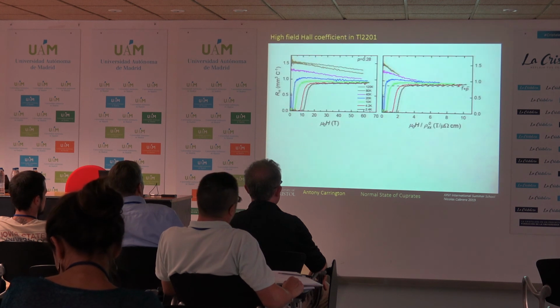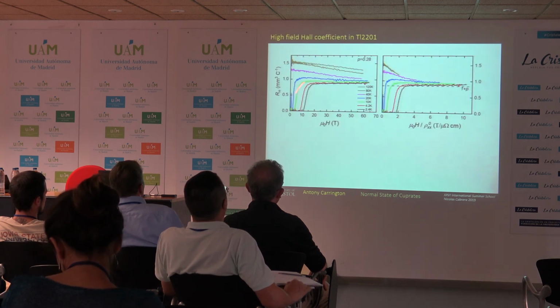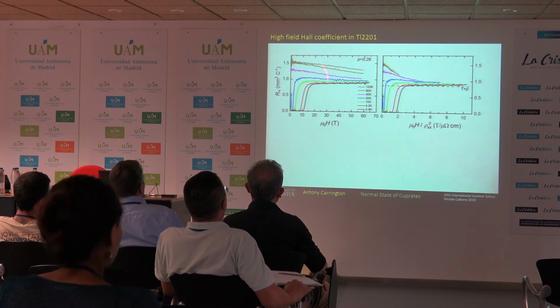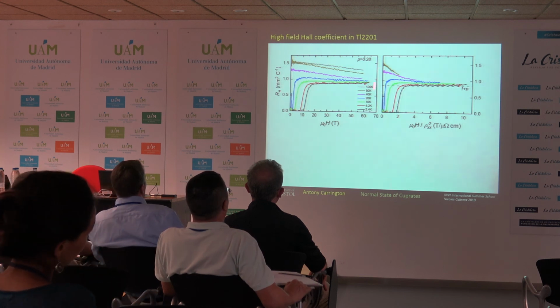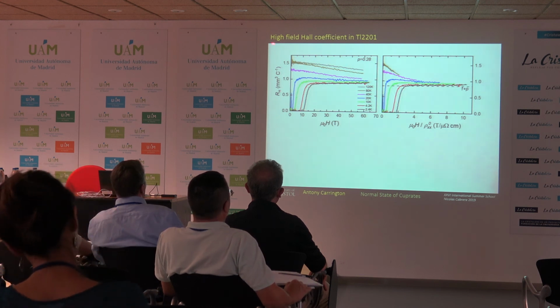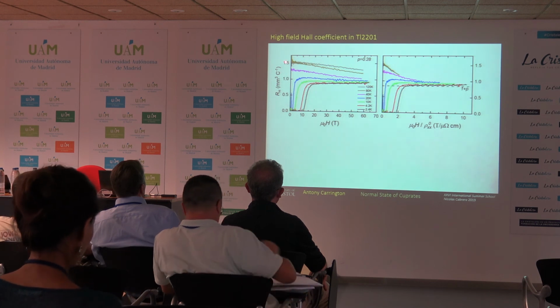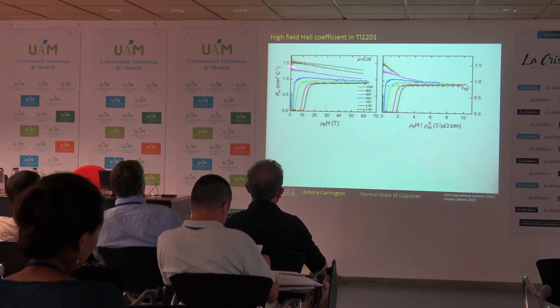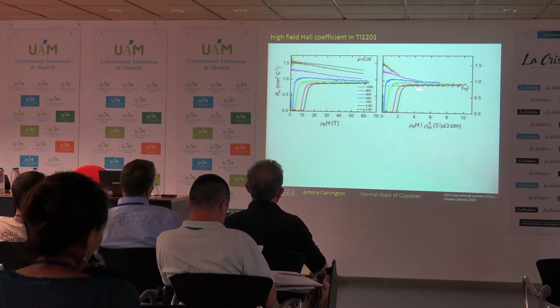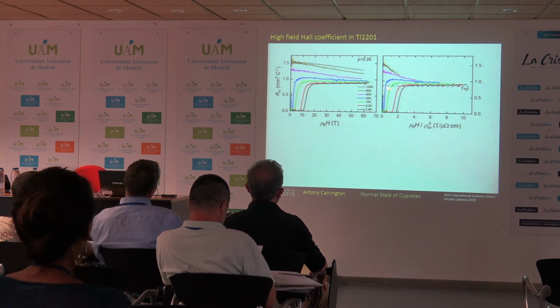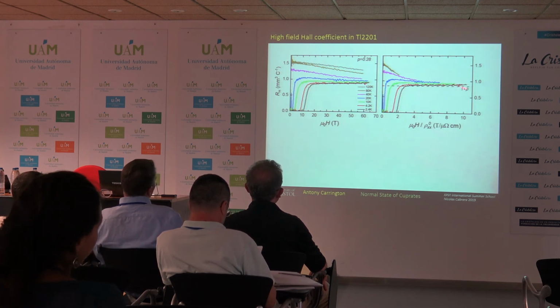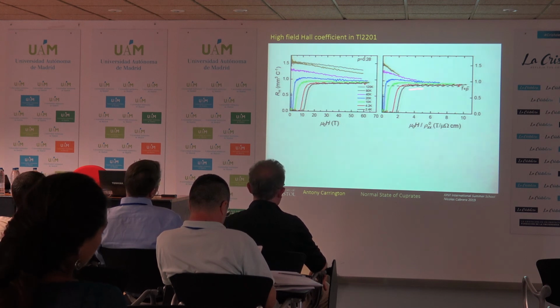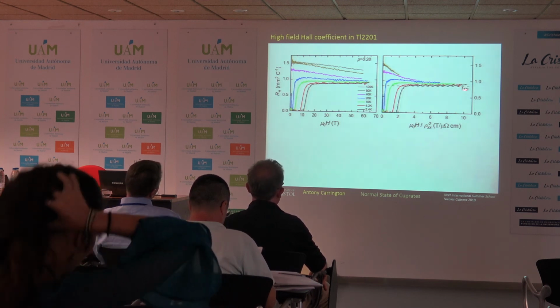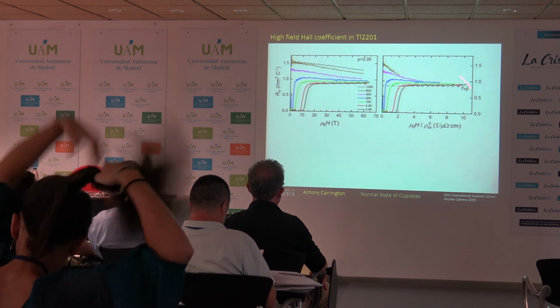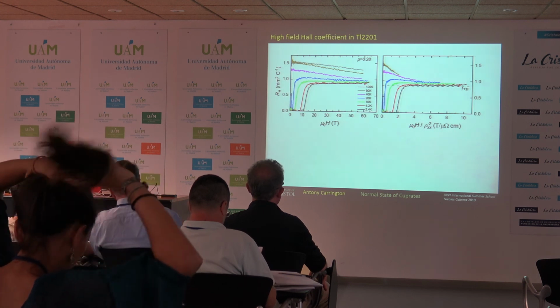And indeed, that is exactly what you find in the experiment. So this is experimental data up to 60 Tesla, Tl2201. Sorry, I missed off the line here, but this line is this line here. So this should be the carrier density, 1 plus p. And you can see that at high enough field and low enough temperature, it asymptotically approaches that.